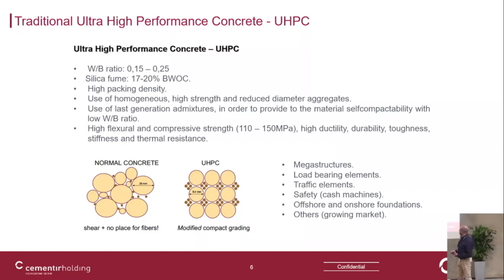Also, ultra-high performance concrete is characterized by a high packing density. So the granulometric curve and the fine fractions are very important. We also use a low sand fraction, which goes up to a maximum of 3 millimeters, and the reason is to have a good packing density. So it's more in the category of mortar that we are working than real concrete. Another condition is to have a product that is self-compactable, self-leveling, and therefore we add some superplasticizers already present in the product.